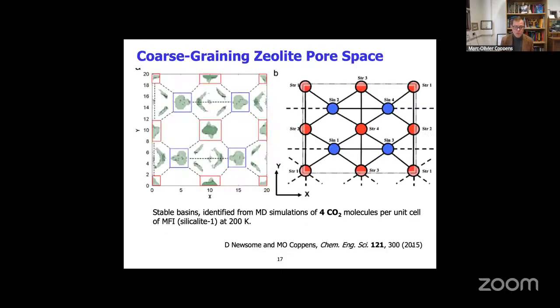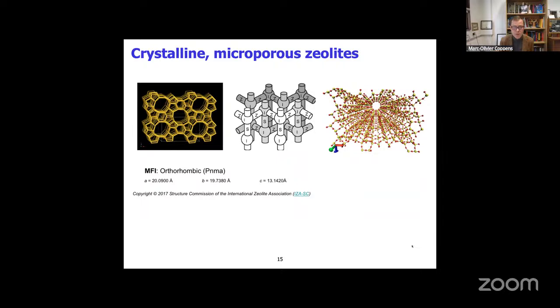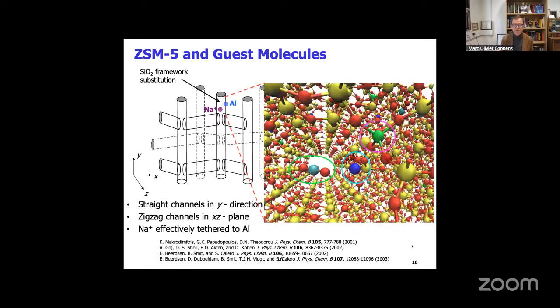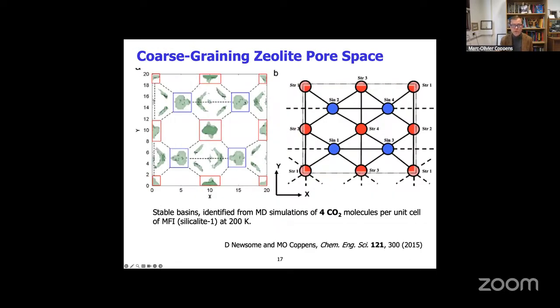We've done such work with former postdoc David Newsome, where we looked at molecular dynamics simulations in this space, and where we were interested in seeing where the molecules spend most of their time. And interestingly, we find it's not necessarily directly related to the geometric depiction that you see here with these intersections, zigzags, with these connectivities of 4 in the intersection channels, but we find an effective connectivity that's quite different in the sinusoidal channels, using the basins where molecules spend much of their time. Say here at 200 kelvins, 4 CO2 molecules spend a lot of time there, and then they hop between them. We can use transition state theory to calculate rates in between them, and we find an effective network that is not necessarily the same as the original network we see geometrically.